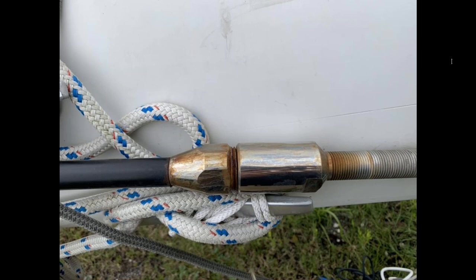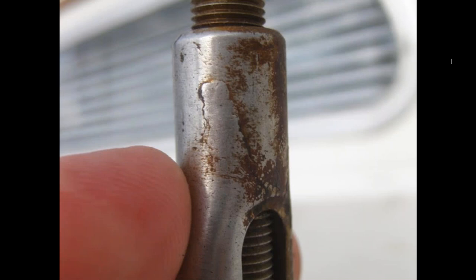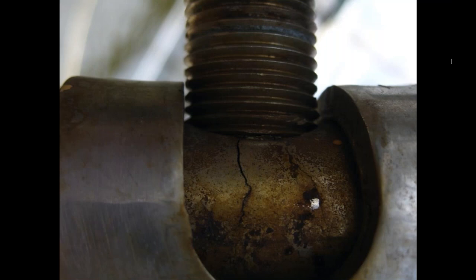Mechanical fittings — I've installed quite a few of these over the years. They're great. This one is only maybe a year and a half to two years old. The problem is the plastic cover on a lot of catamarans' standing rigging — it covers the wire, traps the salt, there's very little oxygen, and crevice corrosion develops. We're seeing the rust running out from underneath the plastic cover onto this mechanical fitting. Turnbuckles — after 10 years I start seeing cracks like this; this one is probably more like 20-some years old and it's becoming quite bad. This is a toggle with a T-fitting — take a close look at these, especially at deck level. You can see one, two, three cracks in here total.